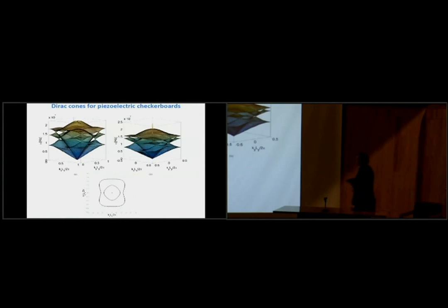Now, if I plot the isofrequency contours, also known as the slowness contours, then I can see this negative refraction, and this is indicated by the non-convex shape of these contours. So in a way, if I take a wave vector, okay, from the origin to that boundary, then you can see that the normal to that boundary will be in the direction which corresponds to a negative angle. And the normal is the vector which shows you the group velocity, the direction of the group velocity. So that's a very sort of brief outline, but I hope I have conveyed the message that the interfacial effects in structures like piezoelectric checkerboards are very, very exciting.